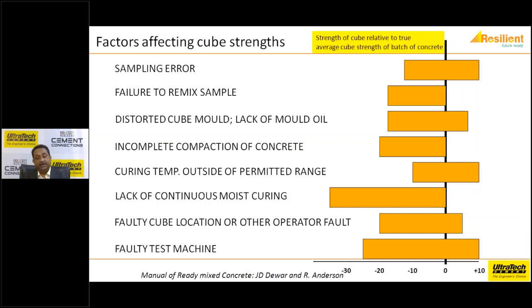Curing temperature outside the permitted range. Your permitted range is 27 plus minus 2 degrees centigrade. If you cure it higher or lower, you will have different kinds of strengths. The lower the temperature, the lower the strength. With higher temperature, you might end up with increased strength.